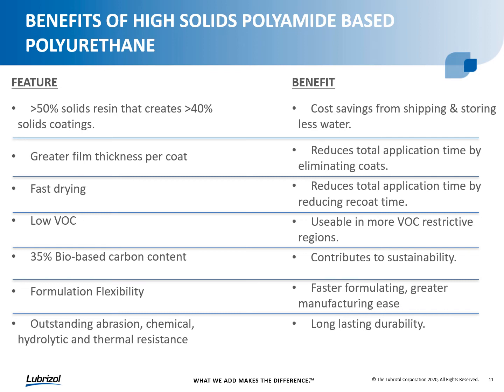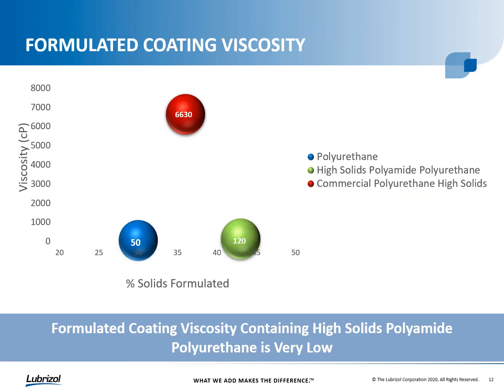long-lasting durability and appearance. One of the challenges with making higher solids resins can be trying to keep the viscosity within a normal range. And what we see here with the high solids polyamide polyurethane is we were able to push the solids higher, but to maintain a very low viscosity of less than 500 centipoise, much in line with a number of our other PUDs in our portfolio.